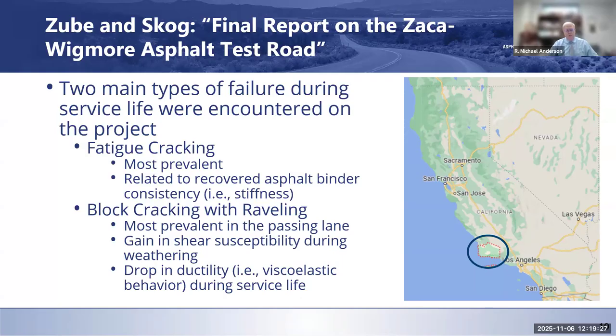First was fatigue cracking, and they said that was the most prevalent overall. And that was related to recovered asphalt binder stiffness. And so at least a large part of that, the consistency of the recovered asphalt binder, was related to the dissipated energy, or G star times sine delta. So from that standpoint, they looked at that parameter and they said, okay, that's the reference for what we're going to look for in a fatigue parameter within the PG system.